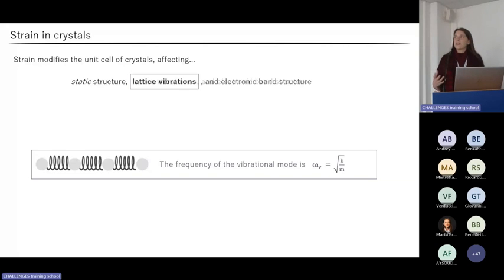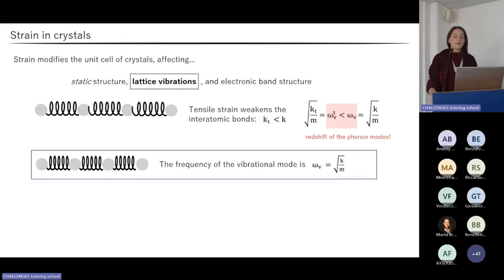In order to understand the effects of strain application on the vibrational properties of crystals, we can rely on an extremely simple model in which the system is thought as a set of massive points connected by springs. In this very basic picture, the interatomic interactions are accounted for by the elastic constant of the spring K, and the frequency of the vibrational mode is given by the square root of the elastic constant to mass ratio. When we apply a tensile strain to our lattice, the interatomic distances increase and the interatomic interactions reduce.